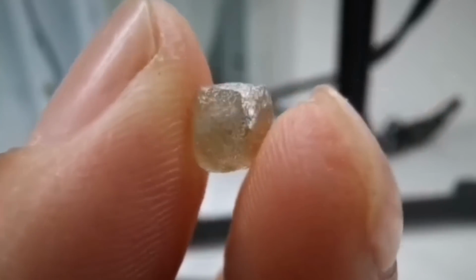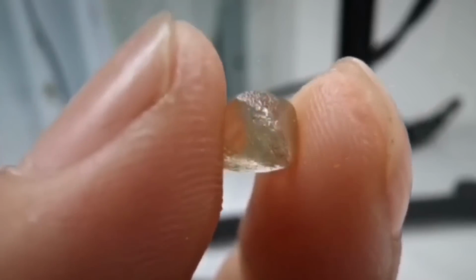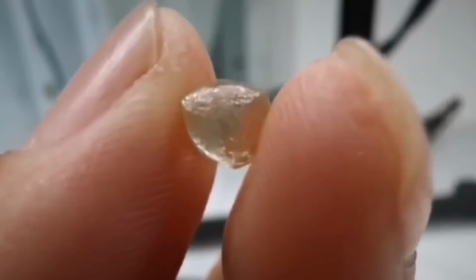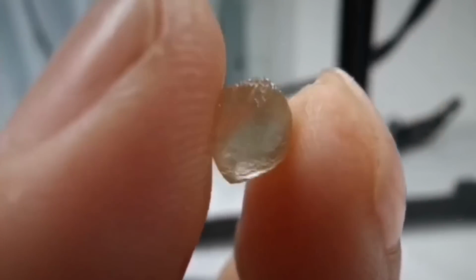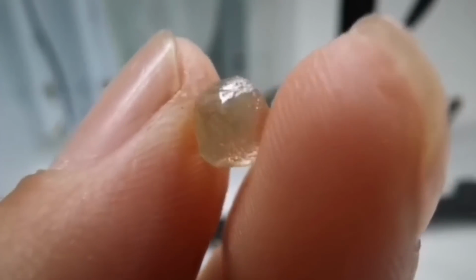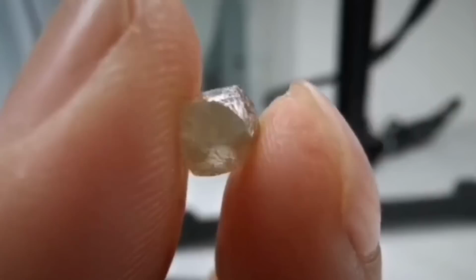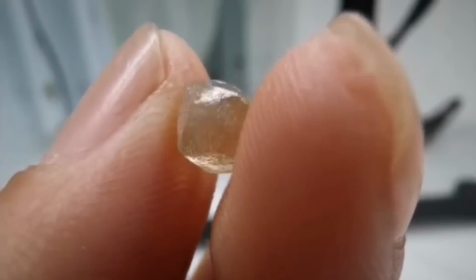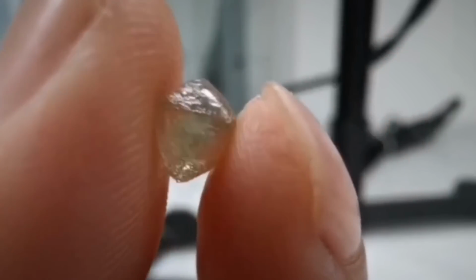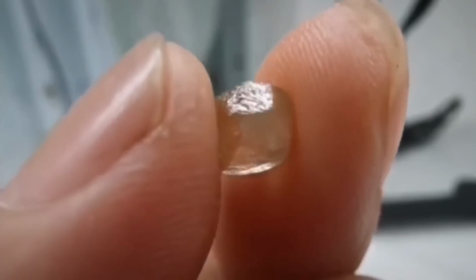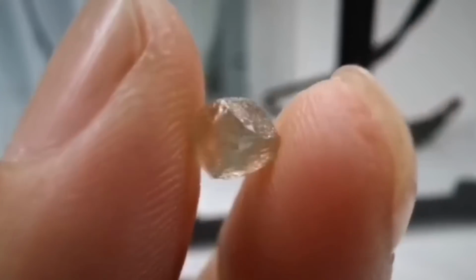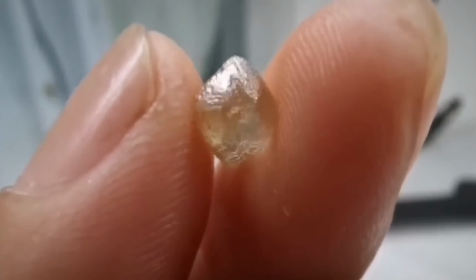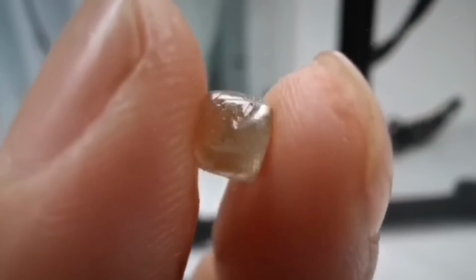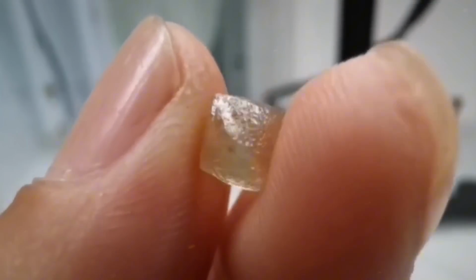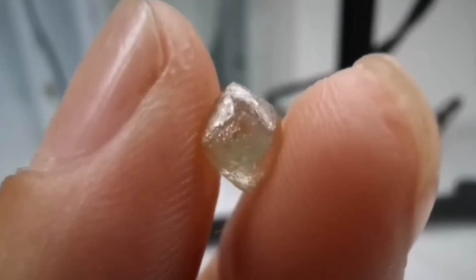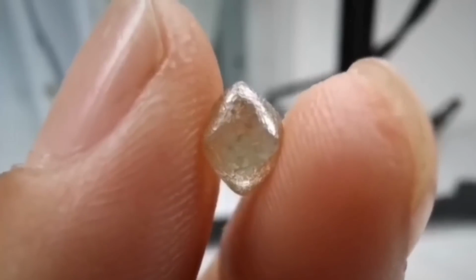When it escalates to lab testing: not after the first visual hit, but once multiple field positives from a tight cluster confirm a trend. At that point, submitting 3 to 5 candidate stones, ideally from different but adjacent sample nodes, allows labs to detect pattern consistency. If all 5 are confirmed diamonds and the mineral inclusion suggests a single source lithology, your case for a viable deposit becomes exponentially stronger. As part of this verification plan, incorporate specific gravity testing.